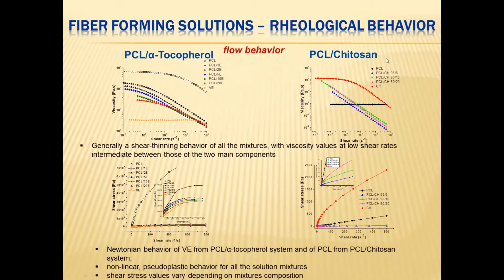In the case of the PCL chitosan system, only PCL presented Newtonian behavior, while chitosan and all the PCL chitosan mixtures behaved as non-Newtonian fluids. These differences in behavior can be attributed to the different solvents that were used. For the PCL alpha-tocopherol system, the solvent was dichloroethane, while for PCL chitosan, the common solvent was acetic acid.